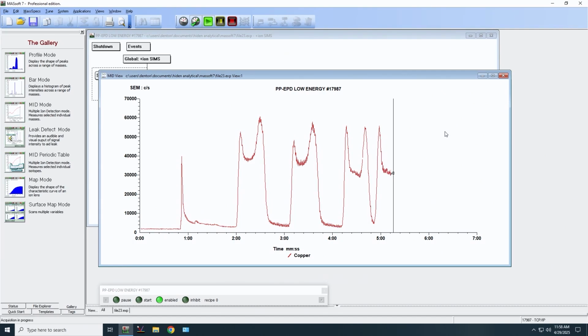So this chip has copper 50 nanometers, that's this one. Next is silicon 60 nanometers. Then there's copper 50 nanometers, silicon 60 nanometers, copper 40 nanometers, and this is silicon 20 nanometers. So even with just 20 nanometers in between the copper layers, it drops almost to baseline, and there's good separation between the layers. This is the last layer, which is another copper 40 nanometers. After that finishes, this chip will be done.